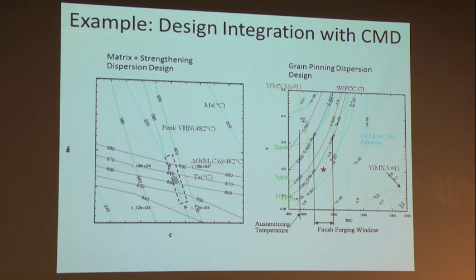And then superimposed are the constraints for processability: the martensitic transformation temperatures need to be high enough to get a fully martensitic microstructure. And then there's a constraint of the solubility of the carbide formers, which gives us these contours of solution temperatures. So this is then the final stage of structure in the last stage of tempering that determines the final strengthening potential of the steel.